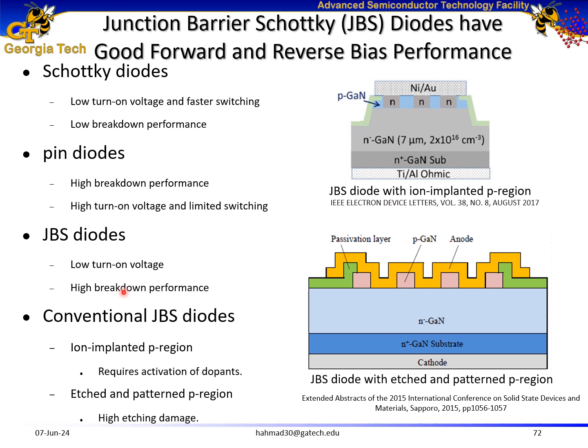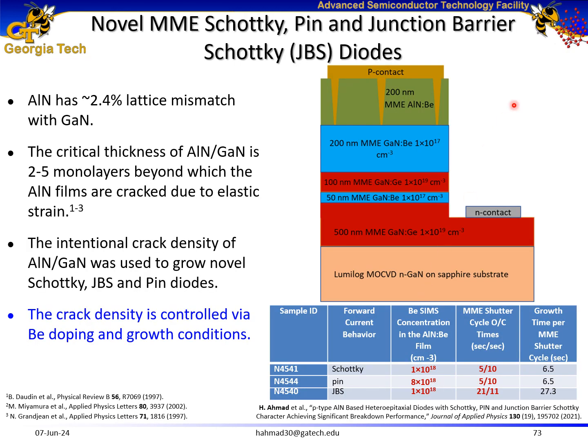Currently, there are two approaches for conventional JBS diodes. One involves ion implanted p-type regions, but it requires activation of the dopants. Another approach requires etched and patterned p-type regions, and it suffers from high etching damage. So we introduced a novel approach to grow MME Schottky, pin, and junction barrier Schottky diodes.